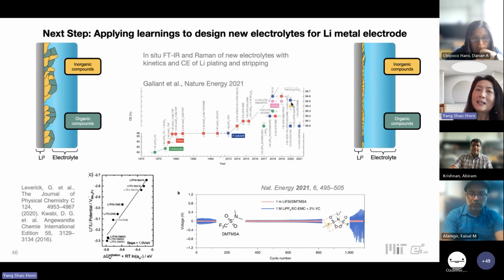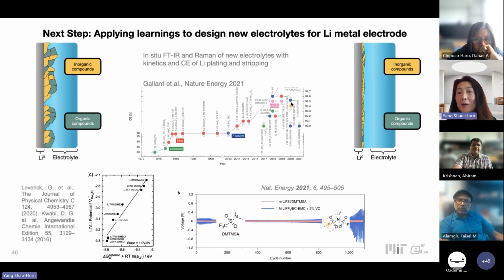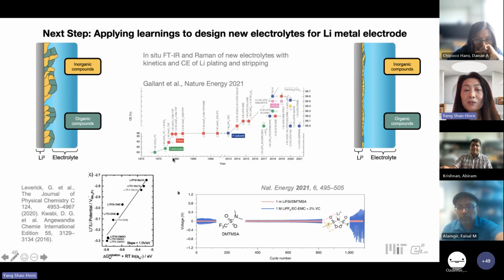99.5%, approaching the possibility that liquid electrolytes may one day also rival the stability, or the possibility of developing pure lithium metal batteries enabled by solid state or ceramic electrolytes. And utilizing electrolytes, particularly utilizing the redox power of lithium, the thermodynamic redox potential is tuned by the solvation environment of the solvent, the solvation environment as influenced by the salt. We can essentially tune the redox potential of lithium by up to 0.5 or 0.6 volt.